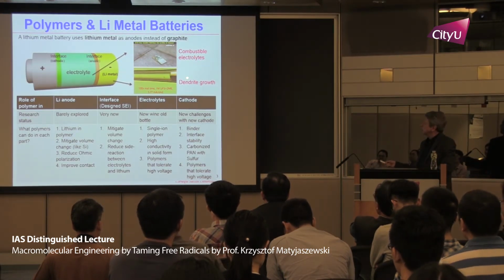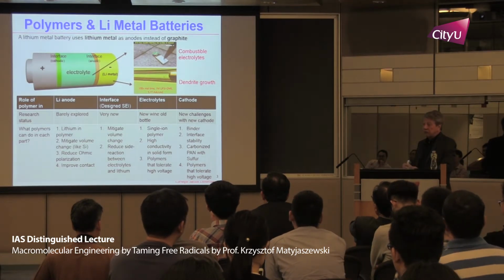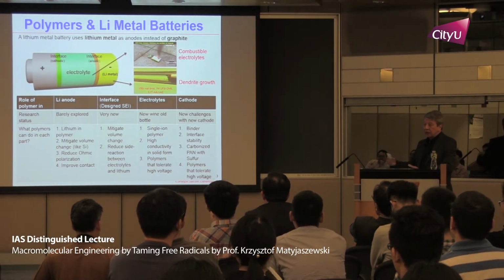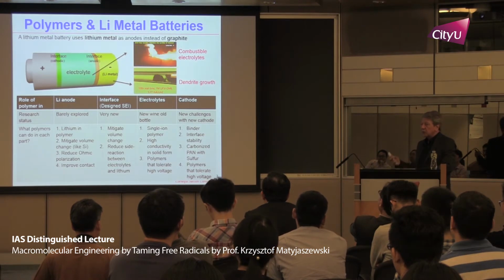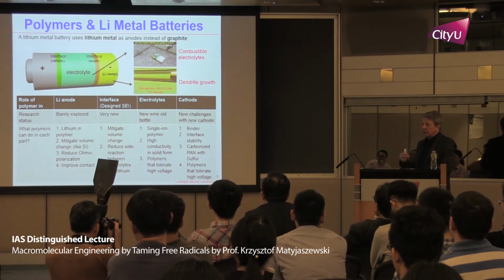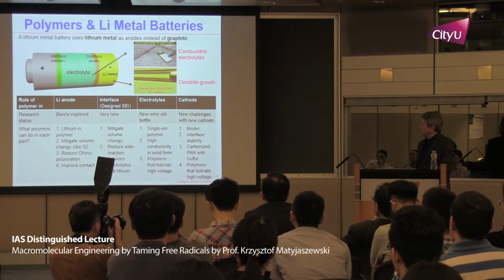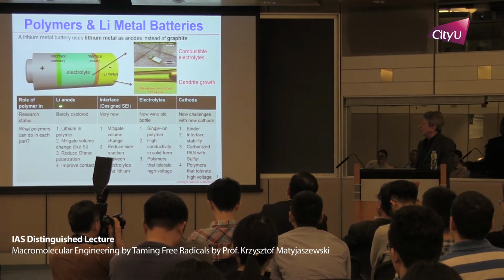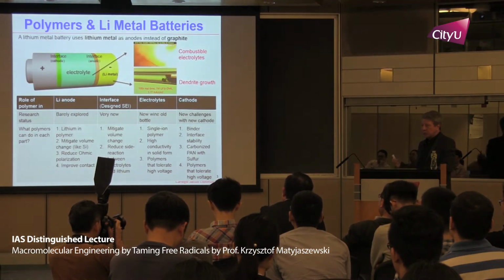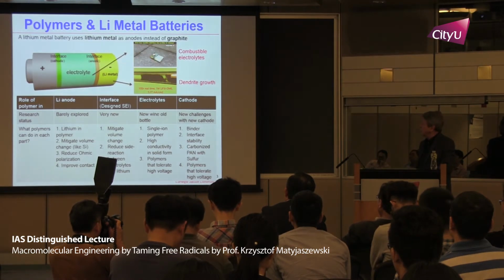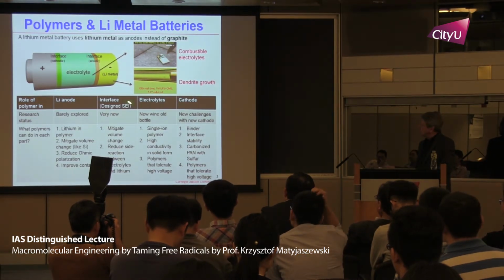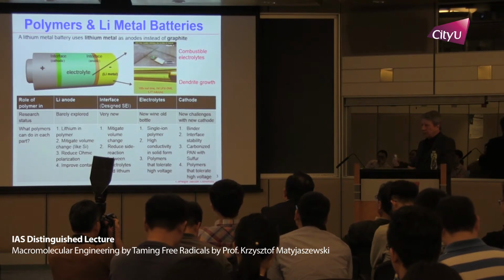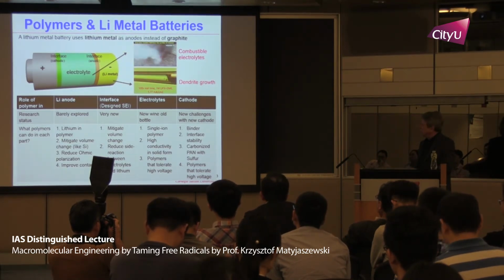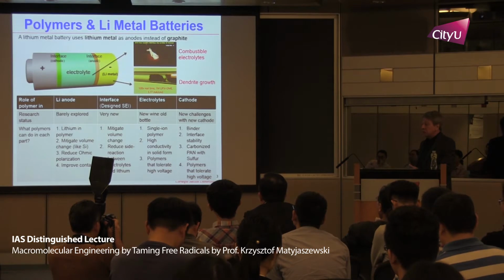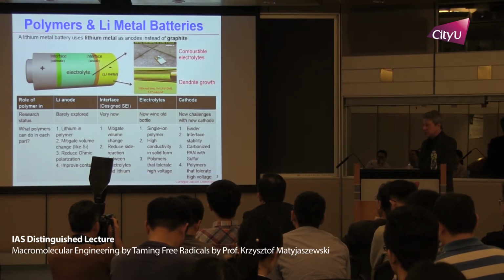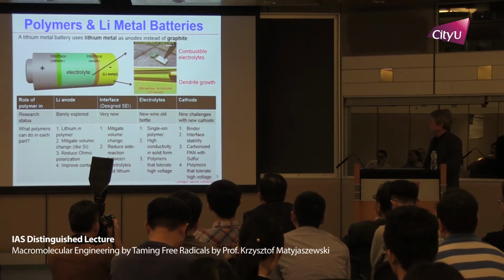It can be used sometimes also to grow a dendrite because they are very soft, and these dendrites can really make a short. So what can we do with polymers in lithium metal batteries? On one side, you can do something with the lithium anode, but this is practically not explored. I will show you one example later. Very important would also be the interface between the electrode and electrolyte, and how you can really reduce different side reactions and also mitigate volume change.